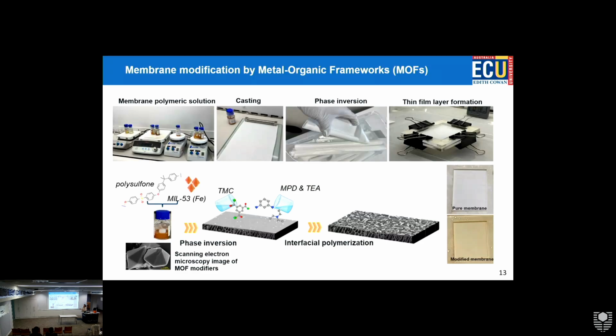So what we do is that we prepare a solution of basically the polymer in a solvent of that polymer. The polymer is normally polysulfone or polyethersulfone. The solvent is normally dimethylformamide or N-methylpyrrolidone, NMP we call it. So they get mixed homogeneously, and then we use a casting knife to cast this solution on the surface of a fabric. It's in an organic solvent, and it goes to a water bath, and in that water bath, a phase inversion process happens. What happens is that the solvent comes out of that polymer solution, and the water goes in and replaces it. So this process makes that membrane precipitate on the surface; it goes from liquid phase to a solid phase, creating those membranes.